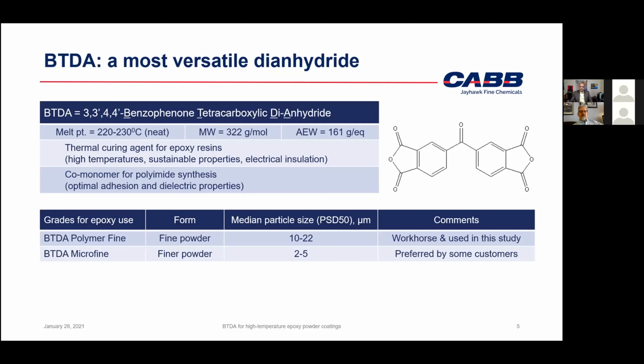And this largely has to do with the behavior, the melt viscosity, and rheology of the base resin that's part of the binder of the powder coating formulation. So in this case, it's important to know we're dispersing a powder curing agent, in this case, obviously BTDA, but during the processing, it was a dispersion of relatively fine particles into the mix, and just keep that in mind.